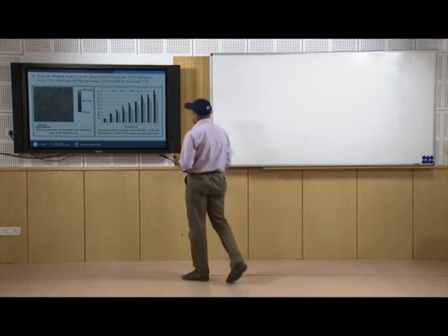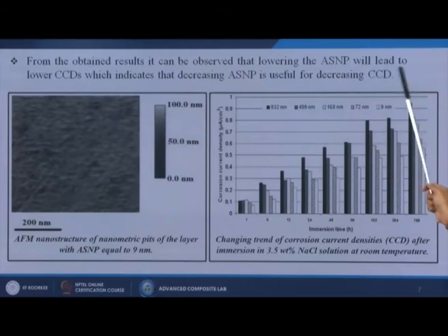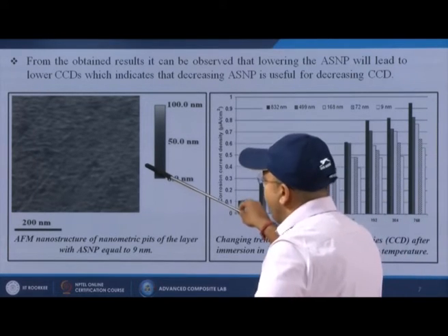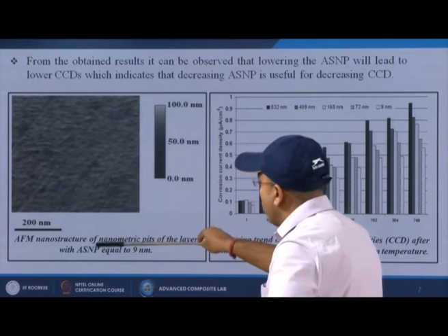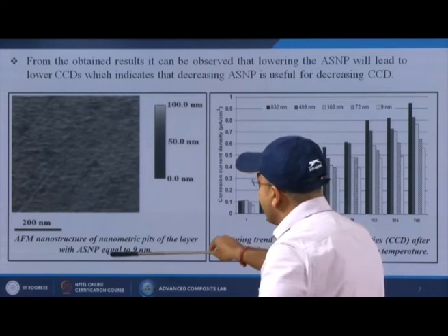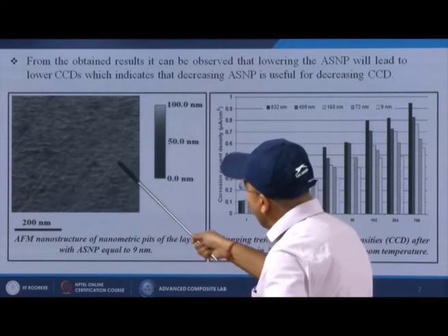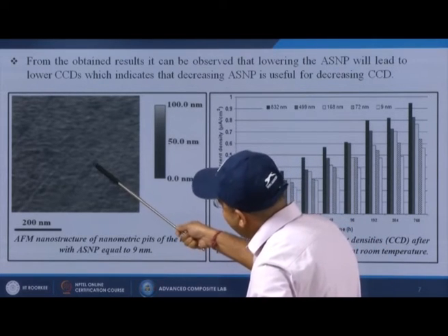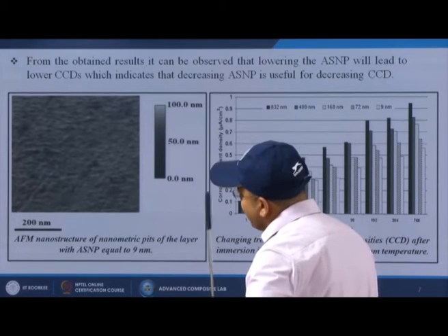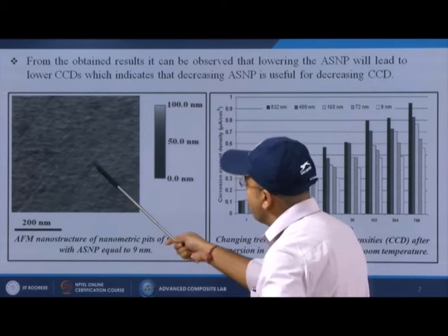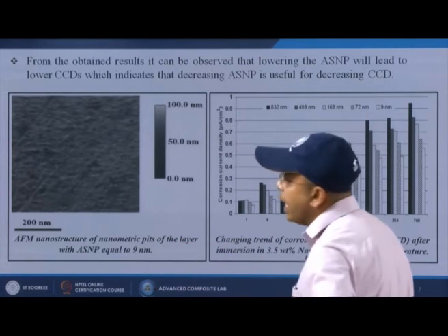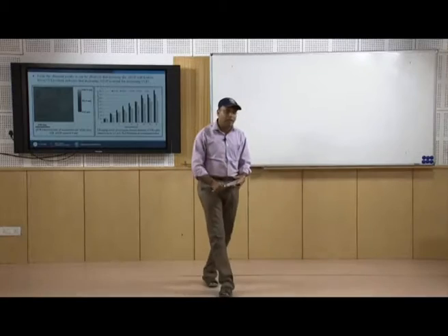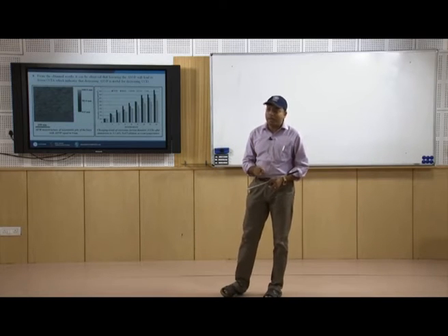From the obtained results, it can be observed that lowering the ASNP will lead to lower CCDs, which indicates that decreasing ASNP is useful for decreasing the CCD. So, here we have shown one kind of AFM, atomic force microscopy, image of nanometric pits of the layer with ASNP equal to 9 nanometer. From this particular figure, you can see that there is some kind of penetrating zone, or maybe some kind of ridges, also some small black holes, which have occurred due to that pitting phenomena by the electrons or maybe by those particular ions.